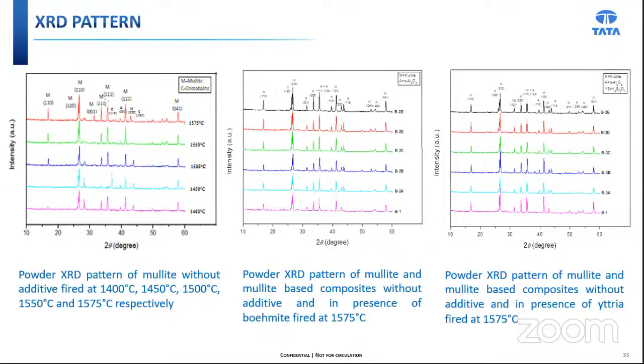This is the XRD pattern. Some typical XRD patterns have been depicted here. The Batch 1 sample on firing at 1400 degrees centigrade exhibits primary mullite as a major crystalline phase, but with gradual rise in temperature, cristobalite disappears with mullite formation, and ultimately at high temperature, cristobalite completely disappears and the mullite phase has evolved.